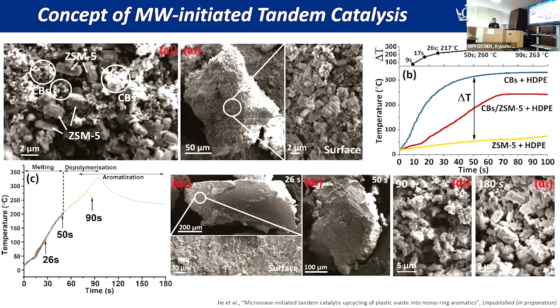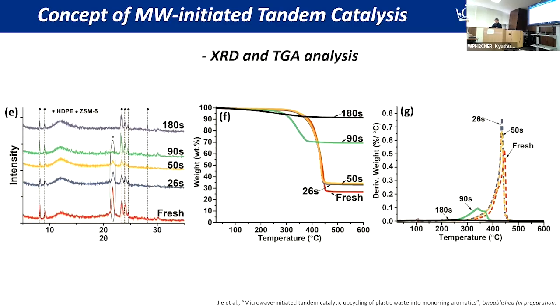It's because at the very beginning, the plastic is actually melting. So when we start the microwave at 9 seconds, it actually embeds all the catalysts inside. And the same at 50 seconds, you will see the reaction has still not occurred, but at 90 seconds, no plastic polymer pieces were observed. All you could detect is the catalyst alone. Further characterization confirmed that. So the reaction happened really, really quickly. It evolved from the start to 50 seconds, and generally the reaction occurred until 90 seconds.